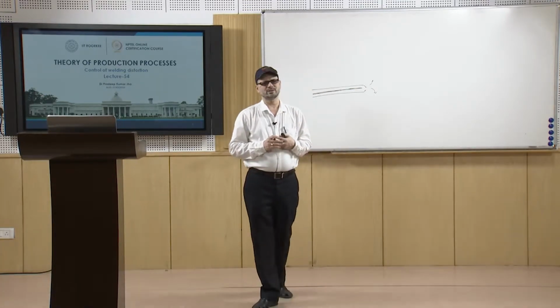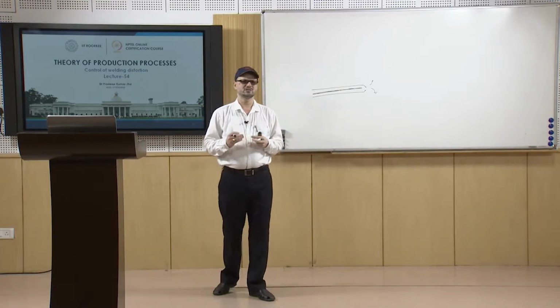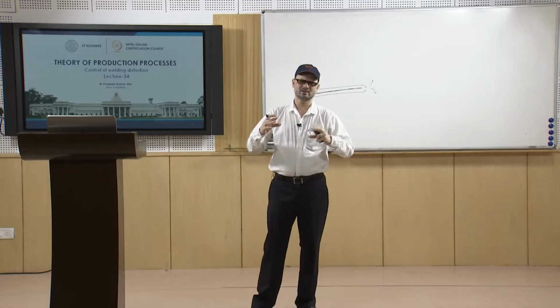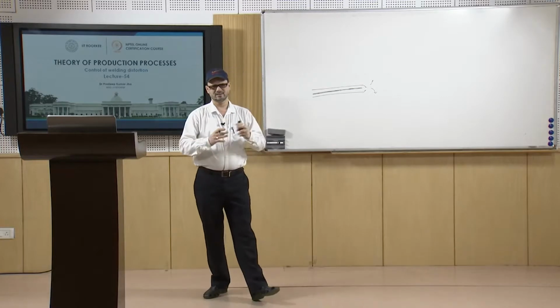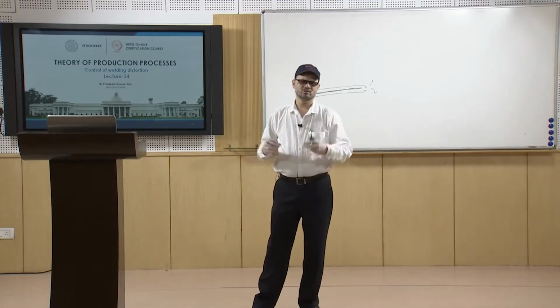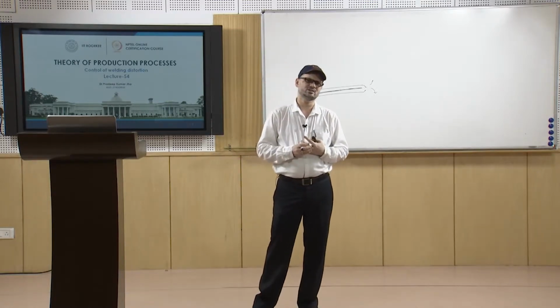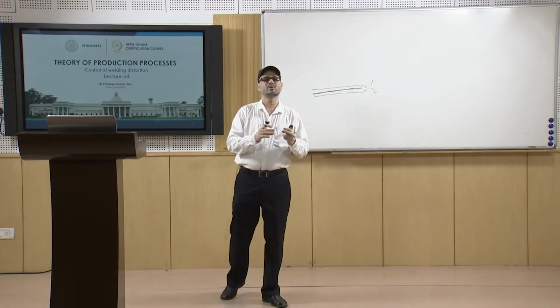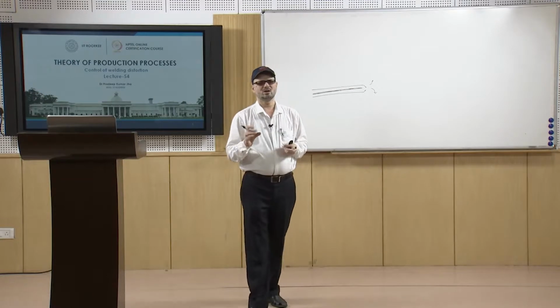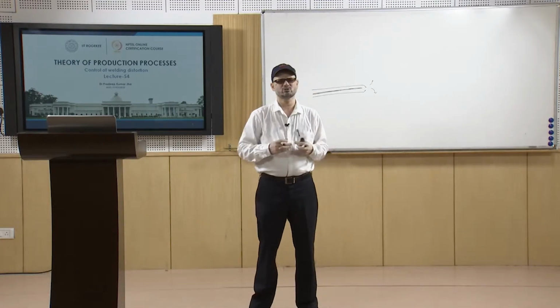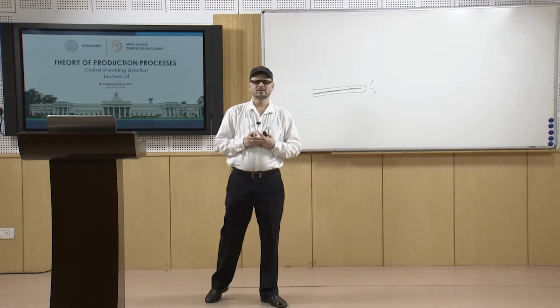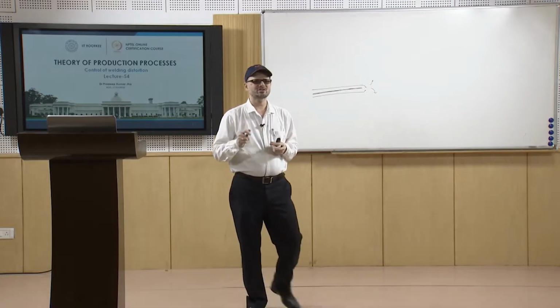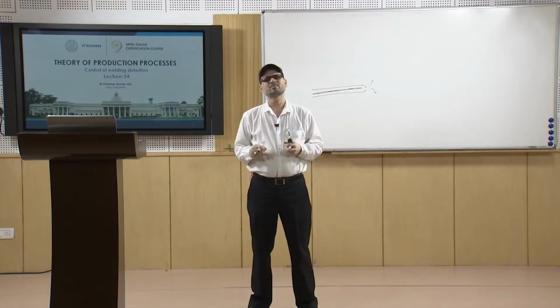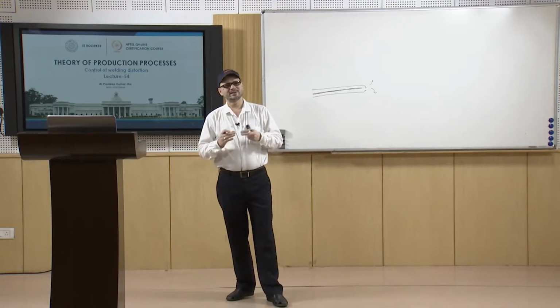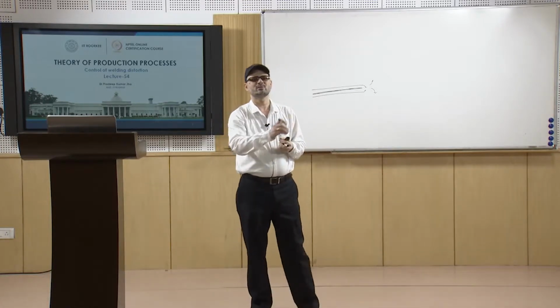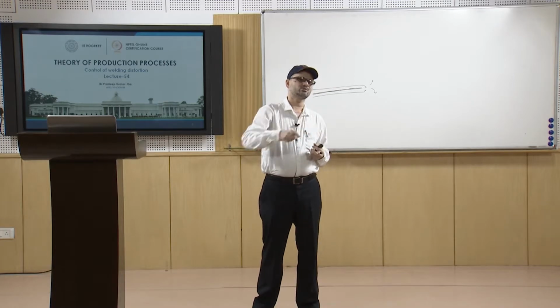Then you have welding sequence. Welding sequence means how you have to proceed in the welding. If suppose you have a particular type of welding structure, then in that case suppose you have transverse welds or you have longitudinal welds. So, if you have plate type of weld structure, cylindrical type of structure which is to be welded, in that case in what way you should proceed, whether the transverse welds should be welded first or longitudinal welds should be welded first. There are certain defined steps which should be followed. Similarly, a backstep welding process is also there, where the welding should be in the backstep manner. So, backstep welding tells you how you have to proceed the welding. In the longitudinal direction you have to go, but then you have to go in a backstep manner.